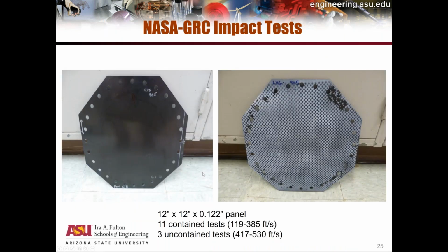So on the left is the panel before it is tested. On the right is the panel after it is speckled. A spray from a spray can of paint is used to paint the front and the back surfaces of the panel. That is then used by the high-speed cameras. Information is gathered, and then DIC is used to find out the full field displacement that is then used to construct the strain field. So they did a total of 14 tests, out of which 11 were contained and 3 were